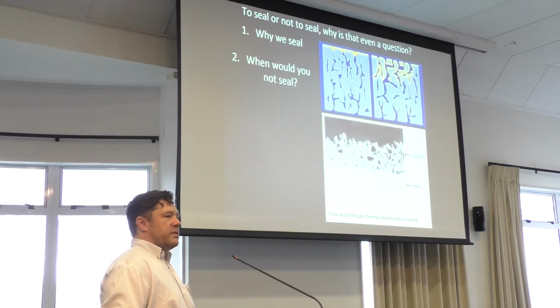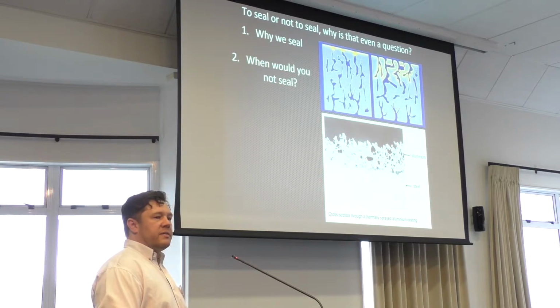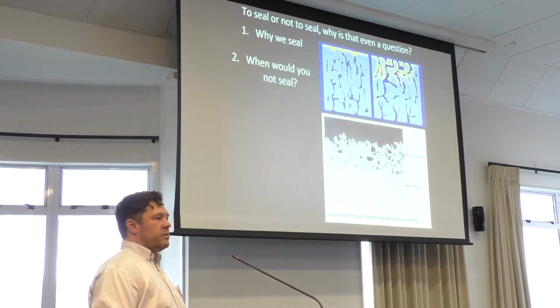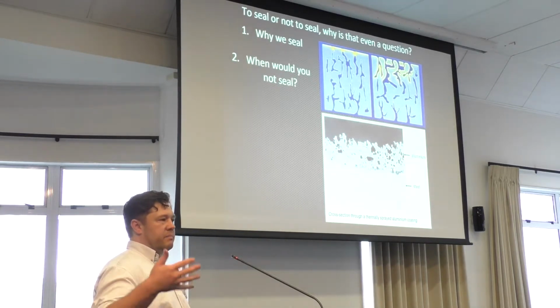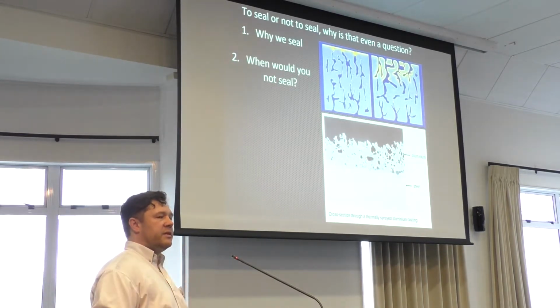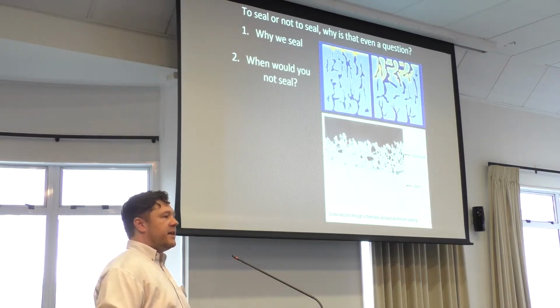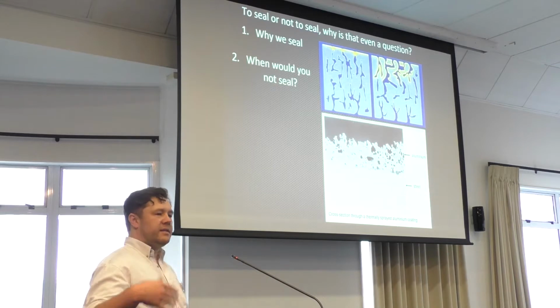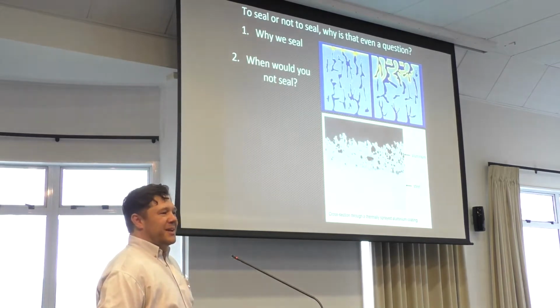The main reason we use it on the aluminium is purely for the client's or the end user's confidence, if you like. When you spray aluminium, it starts to activate a bit slower than zinc, so you get the first sign of corrosion products, which would be like a tea-coloured staining on the coating. Everyone sees that as rust and starts to panic, but it is just the aluminium activating. Once it's activated, that tea staining will stabilise and won't get any further. But explaining that to every end user is not all that easy.